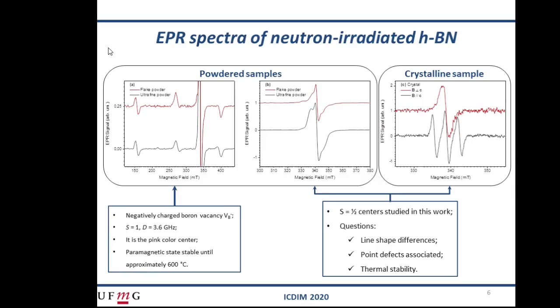However, there are other EPR signals in neutron-irradiated hBN that need more explanation. In these three panels, here, here, and here, we have the EPR spectrum of hBN samples after neutron radiation. In the left panel, this one, is shown the EPR spectrum of the boron vacancy, whose spin Hamiltonian parameters are already known. In the other two panels, here and here, there is EPR data without a model to explain it. These centers both have spin-1/2, and apparently the EPR spectra in powdered samples are more complex than that of the crystalline sample.